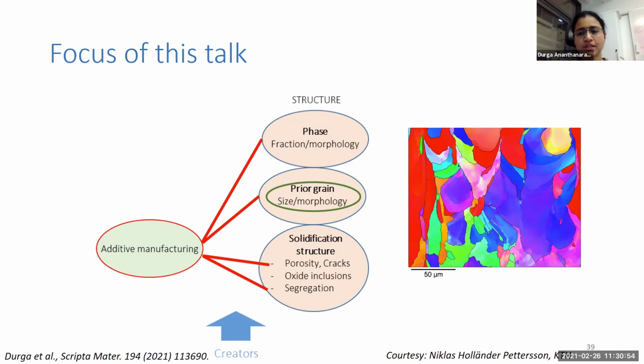So, moving to the next part, which is on grain structure. As I said, we have this typical columnar grain structure that forms in SLM. One of the activities that's been going on a lot is how to make this more equiaxed, so that we have more uniform, isotropic properties, and how do we, in general, control the grain structure.